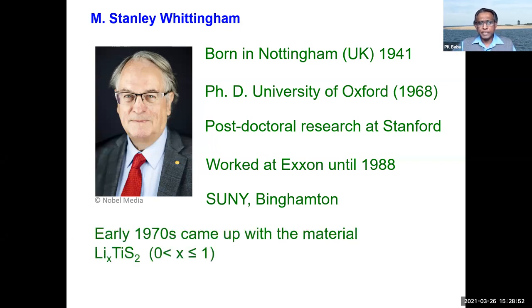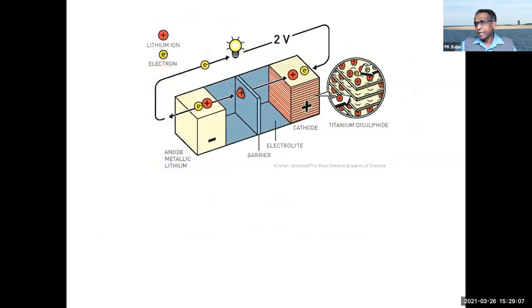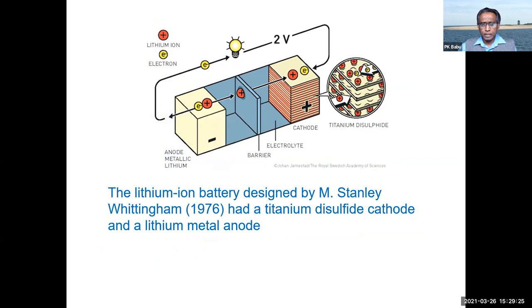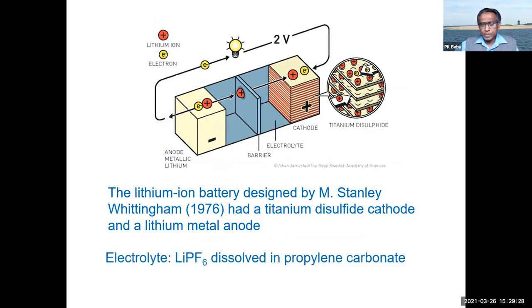In 1970s, Whittingham came up with the material lithium titanium sulfide, Li_xTiS2, where x is a number lying between 0 and 1. And he immediately constructed a lithium ion storage battery. The anode of that was lithium. The cathode used was titanium disulfide. Battery could operate at a potential of 2 volts. And the electrolyte used was a salt of lithium dissolved in propylene carbonate, to avoid using water.